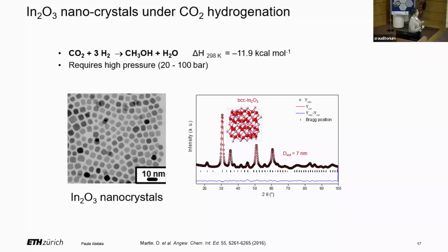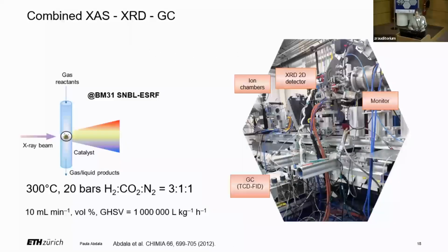So our approach was to synthesize indium oxide nanocrystals and investigate them via combined X-ray absorption and X-ray powder diffraction under operando conditions at the Swiss Norwegian beamline. And to ensure that we are actually producing the reaction we claim, so producing methanol, we connected the outlet of our capillary to a GC that contains a FID detector and allows us to quantify the methanol with a similar time resolution as the spectroscopy data.